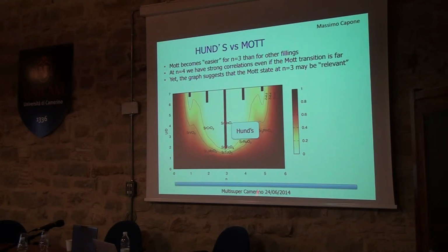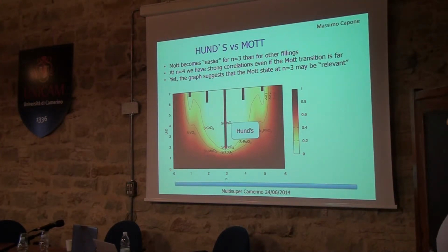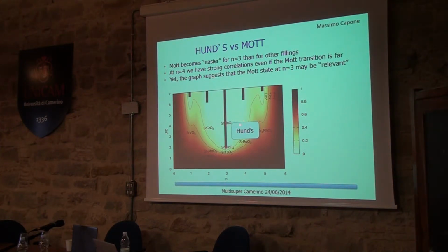While the color scale here reflects the degree of correlation. Essentially, the whiter, the more correlated. So essentially what you see is that the critical U here is small, that was the half-filling, while here it's large. So if you sit here, which would be the iron-based superconductors, it takes a very large U to have a Mott insulator, but still you have a large area of whiteness. Okay, that's what I was discussing before.